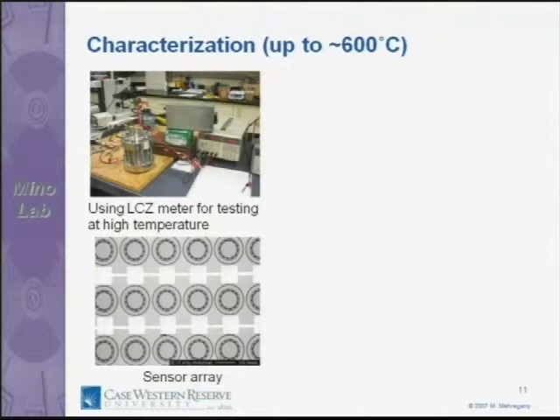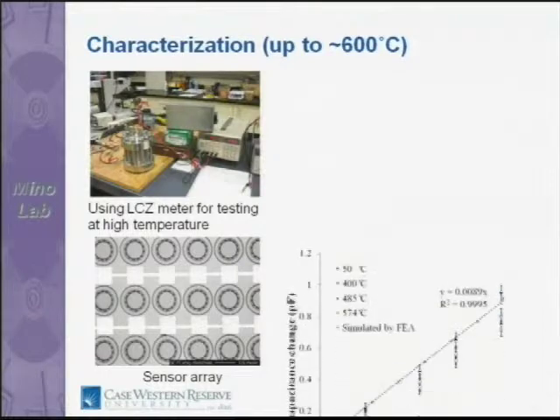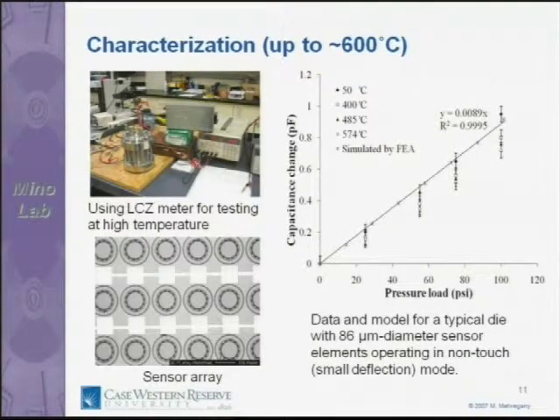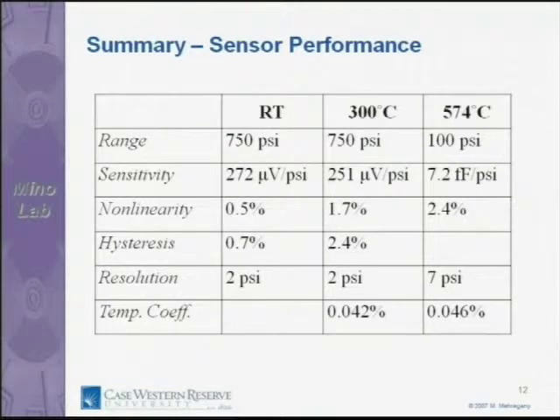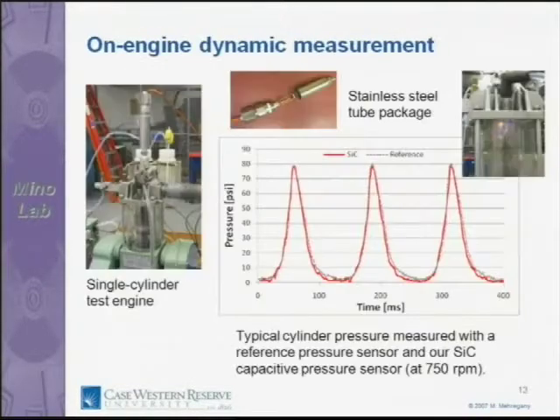So you see a benchtop pressure chamber that my student Li Chen actually designed and fabricated with help from other group members. You see a large number of capacitors put in parallel, pressure sensor elements put in parallel to get a large capacitance change. And what you see here is actually the capacitance change as a function of pressure, pressure load applied to about 100 psi, while the temperature is changed up to 575 degrees, and a reasonably linear behavior from the sensor. So the sensor is actually capable to operate, operation verified to 574 degrees.